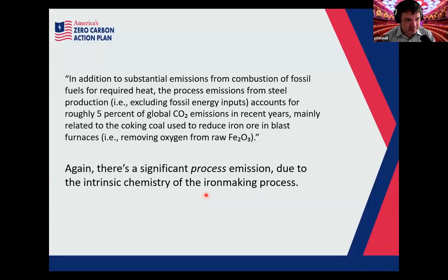Right, iron and steel. Again, similarly to cement, there's a significant process emission. This comes from essentially the use of coal or metallurgical coal to produce carbon monoxide and hydrogen, which you then react with your iron ore, and the carbon monoxide rips the oxygen off the iron ore, and you end up with iron and CO2. You can use hydrogen to do that sort of ripping off process as well. However, you do need a lot of hydrogen to actually do that. So again, there's intrinsic process emissions here.